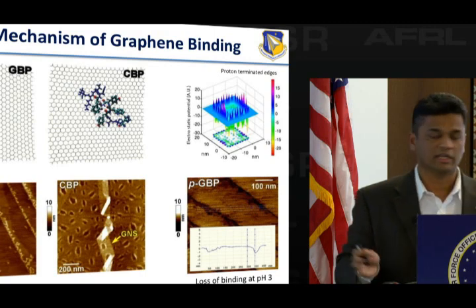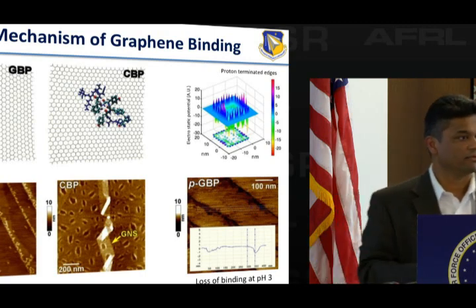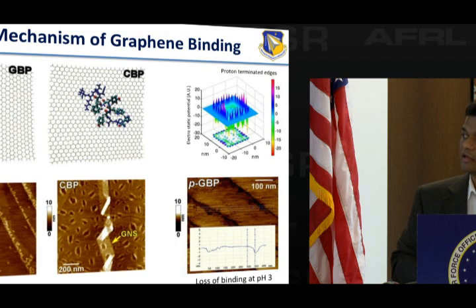We've monitored it using AFM. You can actually see them evolve. So they are just the holes that have been left behind. And it's nice because you can go do AFM and you can actually get a monolayer thickness from that.